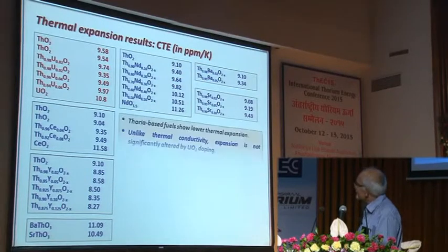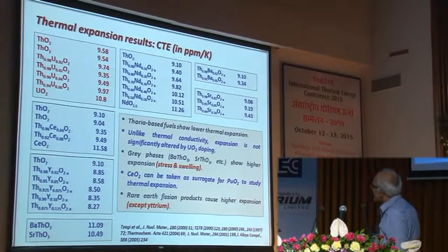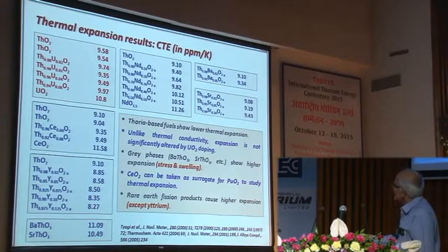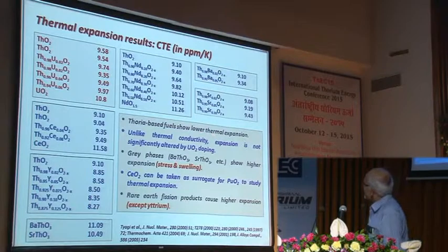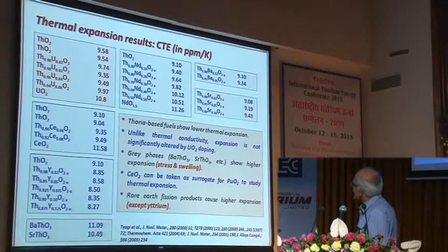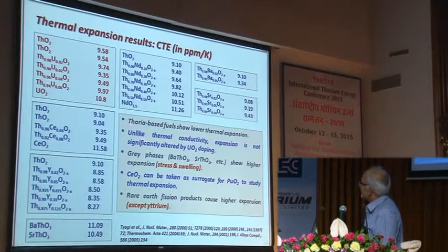The ceria is used as a substitute for plutonium. So you can see from these numbers the thoria-based fuels show lower thermal expansion, and unlike thermal conductivity, expansion is not significantly altered by UO2 doping. The gray phases, here you can identify, show higher expansion, and CeO2 here is used as a surrogate for plutonia, and rare earth fission products cause higher expansion.